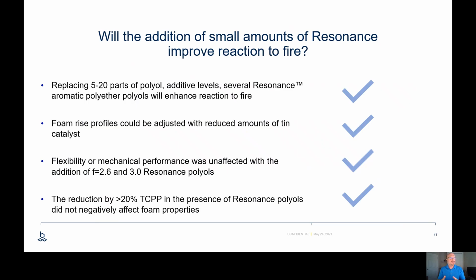Finally, just to summarize, again, the question is, will the addition of small amounts of resonance improve reaction to fire? And we can say yes. Replacing 5 to 20 parts of the polyol at an additive level, in other words, other resonance aromatic polyether polyols, will enhance the reaction to fire, not just maintain it, at even lower levels of fire retardant. At least with this particular system, of course, you would want to consider your own system and do your own testing to ensure this would happen.